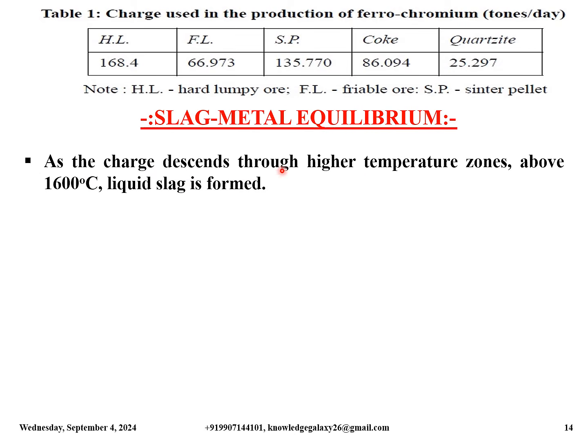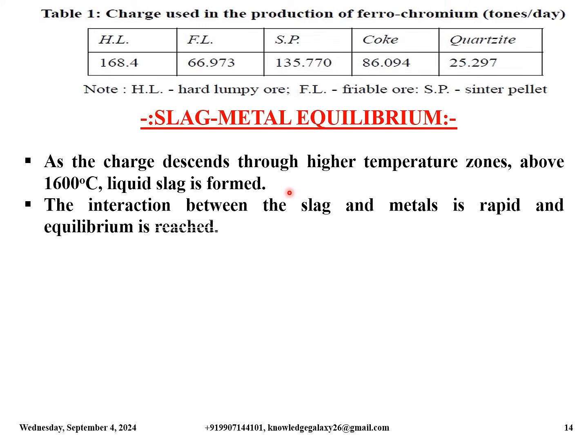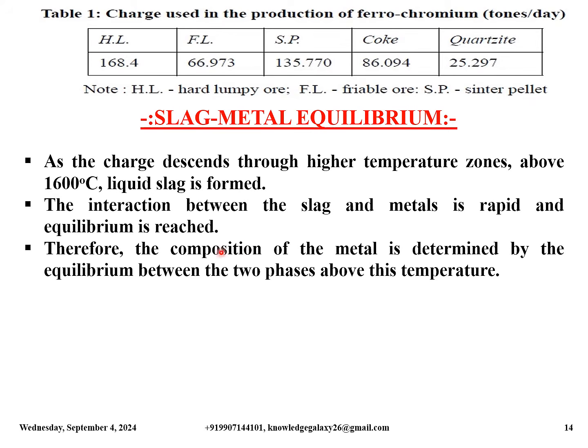As the charge descends through higher temperature zones above 1600 degrees Celsius, liquid slag is formed. The interaction between the slag and metals is rapid and equilibrium is reached. Therefore, the composition of the metal is determined by the equilibrium between the two phases above this temperature.